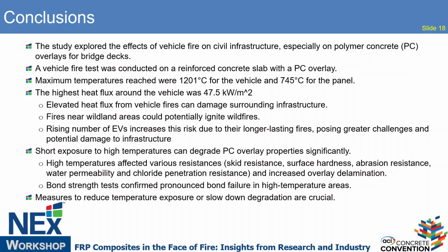Even in our test, the vehicle fire only lasted for 225 seconds, but even such a short exposure to high temperature already damaged the PC overlay properties significantly. It impacts skid resistance, surface hardness, abrasion resistance, water permeability, and chloride penetration resistance, and also increases the overlay delamination, especially in those areas which were exposed to the high temperature.